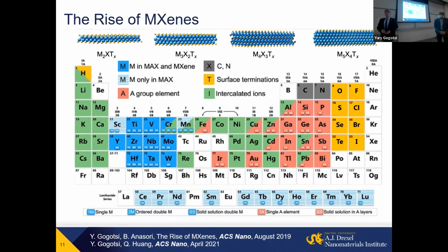They were not predicted to exist in advance. No one really expected that. And this is a combination of, to a certain extent, accidental discovery. To keep a long story short, I had an idea that titanium silicon carbide, titanium aluminum carbide MAX phases can be good for anodes of lithium-ion batteries. It was the time people started to work on silicon anodes.